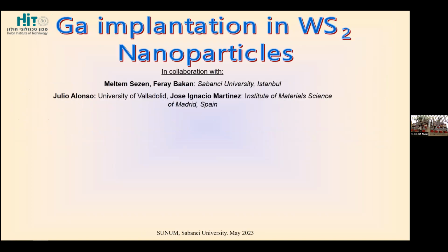One of our research tasks was gallium implantation in WS2. This was done here in Sunum about 8 years ago in collaboration with Laikhtman, and Feray also took part in the later stage of these experiments. And again, very recently, with the help of our theoretician collaborators from Spain, we achieved some results that fully confirmed the results of that experiment that otherwise were not so clear.